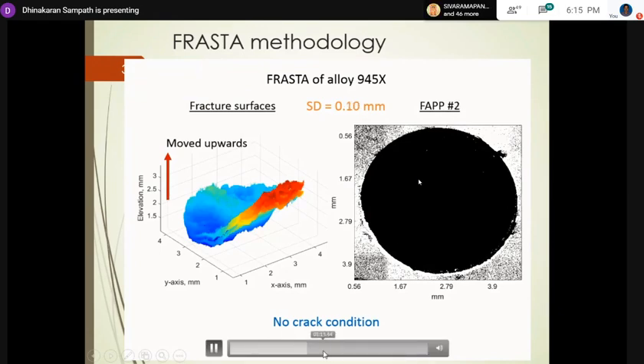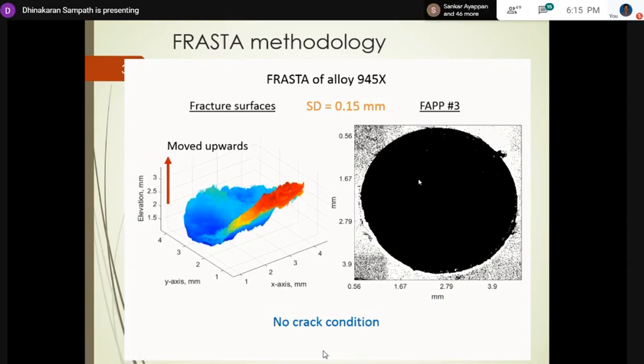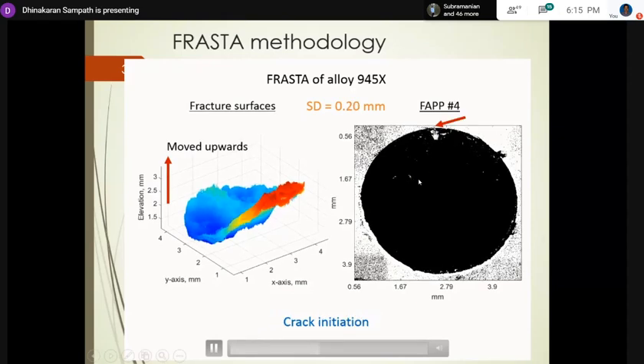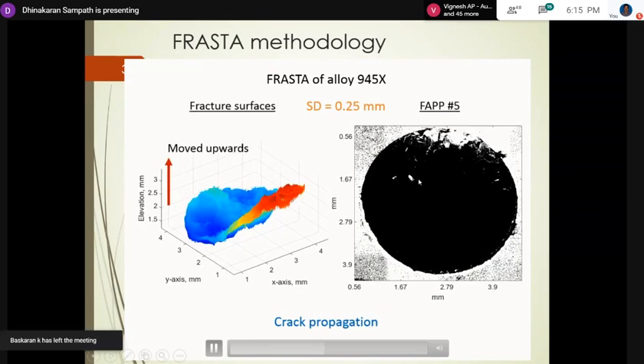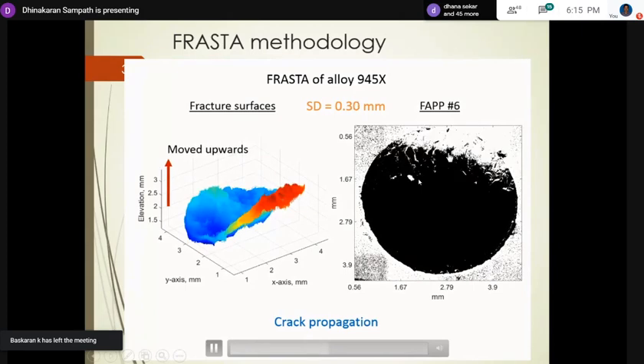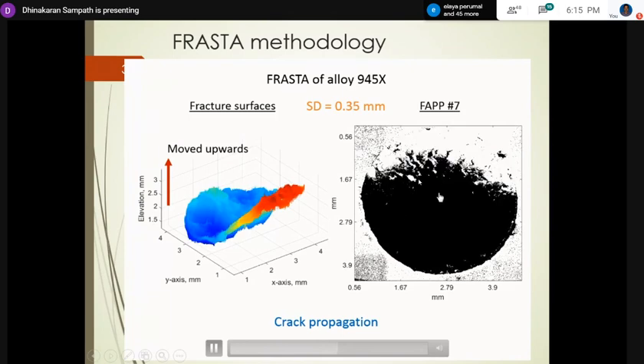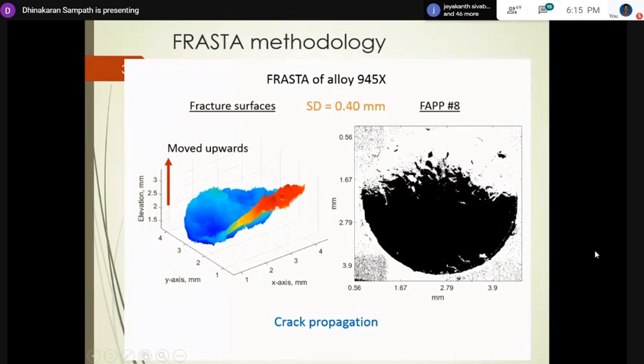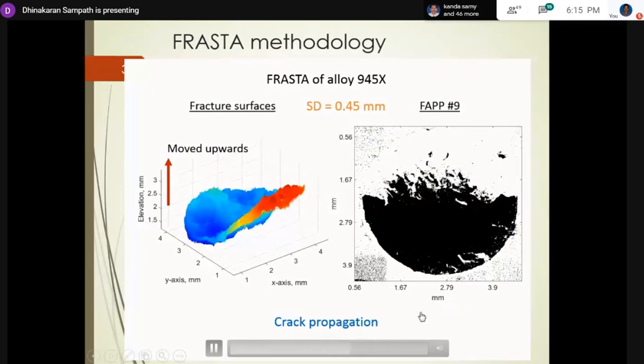crack evolution in multiple steps. Now in a minute we'll see that the crack starts to initiate there, and that's the initiation point, and it starts to grow. We tend to see that it grows faster at the outer surface than in the central region. So now the crack starts to go around the sample where the hydrogen is present in abundance, while the central region had no hydrogen at all.